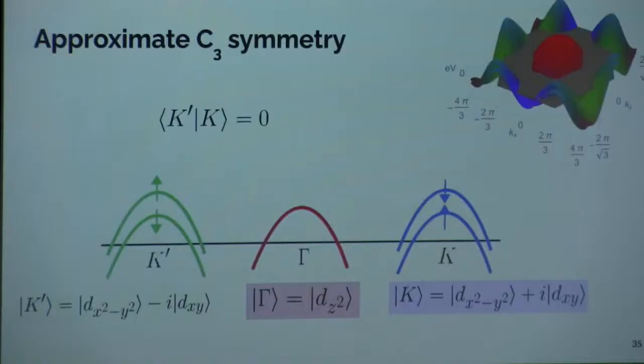So here is the explanation. Here is a simplified picture of the band structure. Although this is a complicated 3-orbital model, we can diagonalize the Hamiltonian exactly at high symmetry points. So solving the Hamiltonian at 3 points, gamma, K, and K prime, we obtain that the orbital content at K is d plus id, at K prime it's d minus id, and at gamma it's d z squared. Now, all of these 3 orbitals are orthogonal, meaning that if we take the inner product, this gives 0. So for the remainder of the argument, I will exclude gamma, but this is really just for simplicity. We can easily reintroduce it at the end.